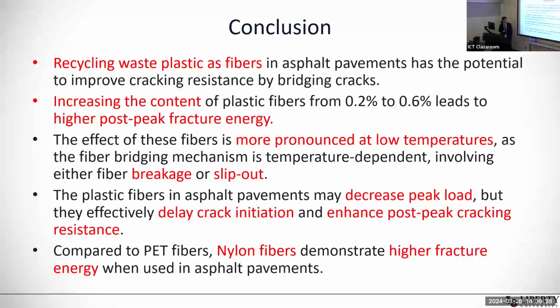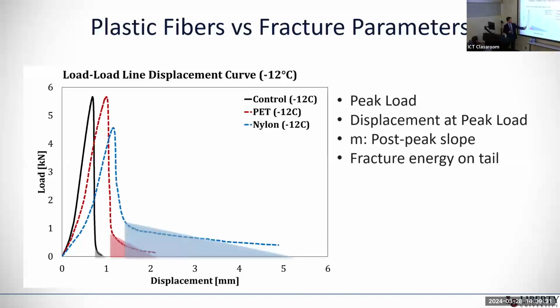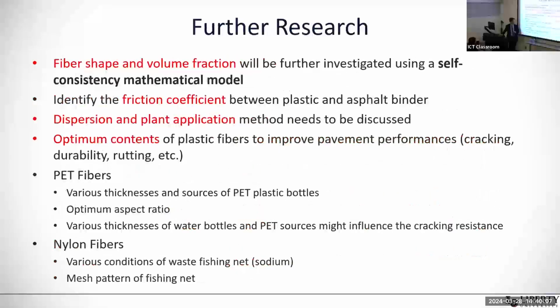Plastic fibers, as you can see here, I didn't mention that one. As we add more and more fibers, it shifts the displacement at the peak load, which means it delays the failure. It actually fails at a higher displacement, but still it drops. When you use nylon, it drops the peak load, but it improves the crack resistance capability after the peak load.